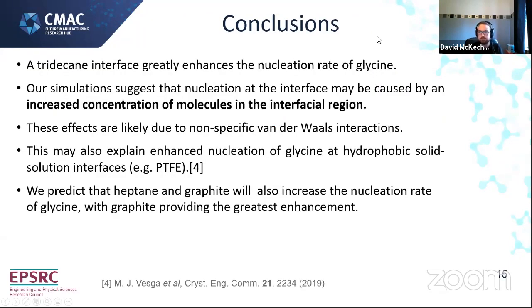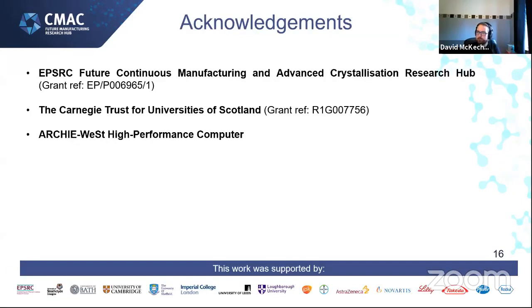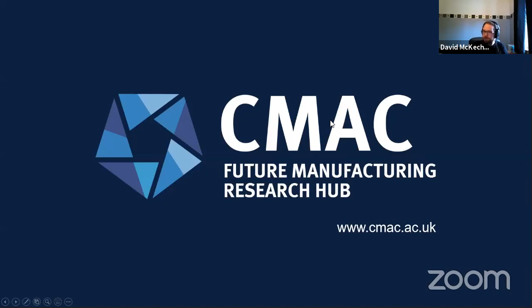In conclusion, we find experimentally that a layer of tridecane significantly increases the nucleation rate of glycine, and our molecular dynamics simulations suggest this is due to increased concentration of molecules within the interfacial region driven by non-specific van der Waals interactions. We believe this will also help explain enhanced nucleation at hydrophobic solid-solution interfaces such as PTFE. We predict heptane and graphite will see similar increases, with graphite giving the greatest enhancement. I'd like to thank the EPSRC for funding this work, the Carnegie Trust for funding the computational work, and Archie West HPC at the University of Strathclyde. Thank you all for listening.